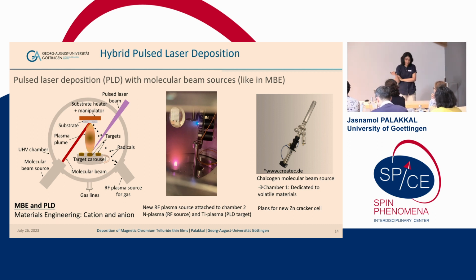Just like in the case of electron beam evaporation, you can use the PLD target for getting cations like chromium or strontium or niobium. But if you want to use a highly volatile element like tellurium, you cannot give the tellurium from a PLD target. In that case, you have to supply it in the form of a molecular beam source. And that's what we are currently developing.